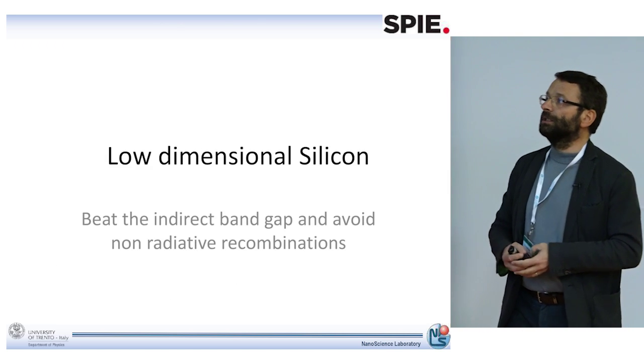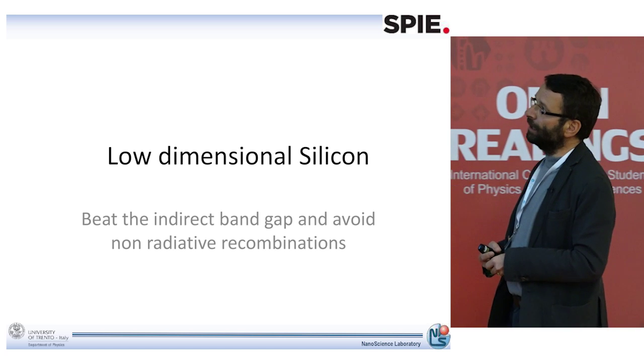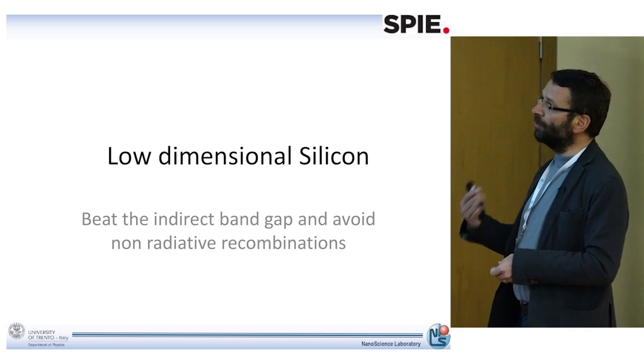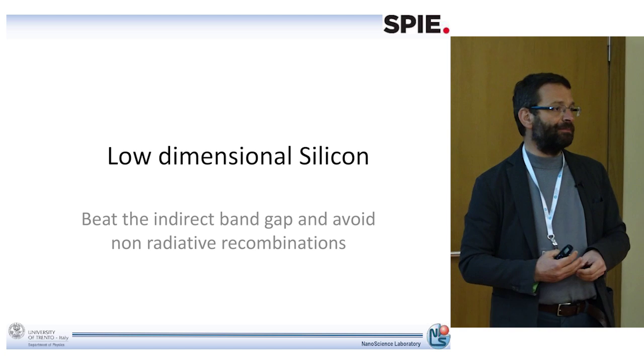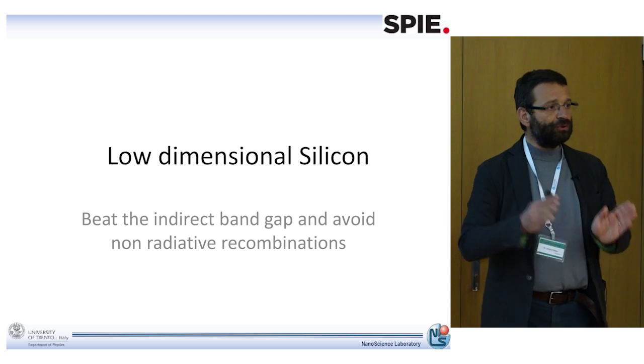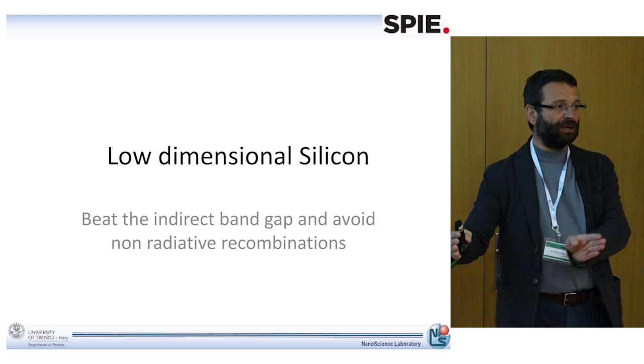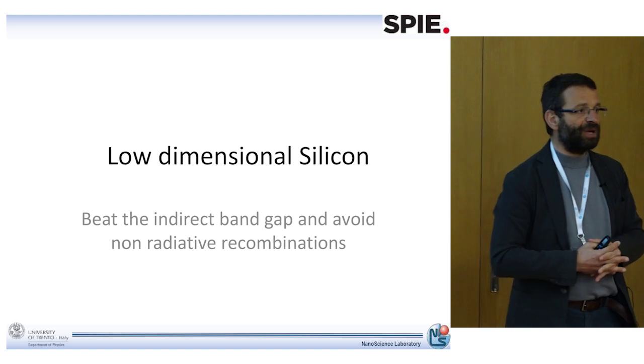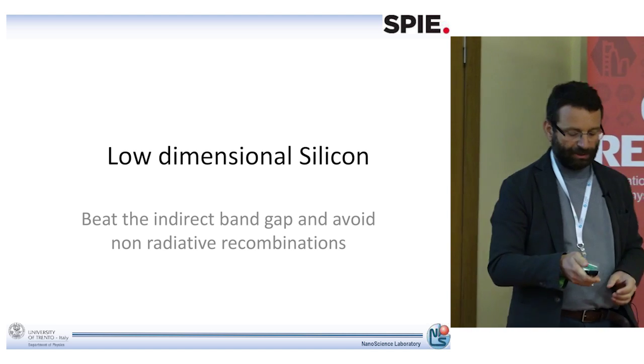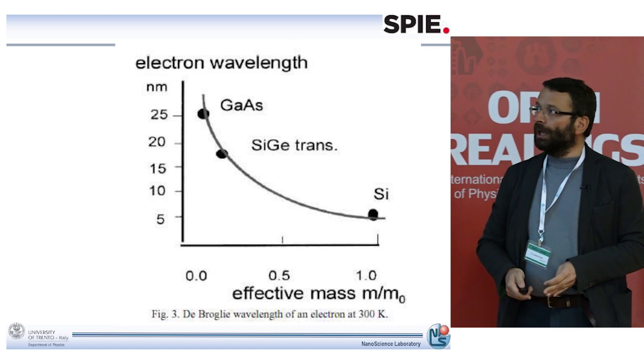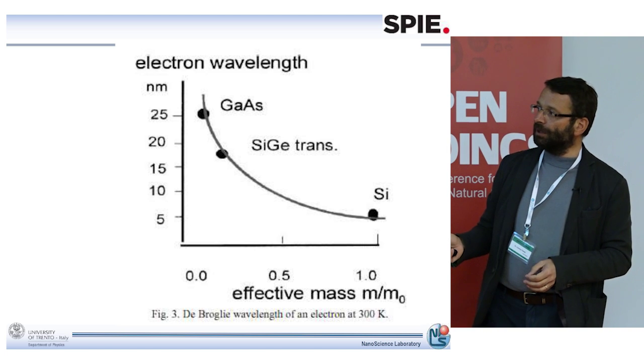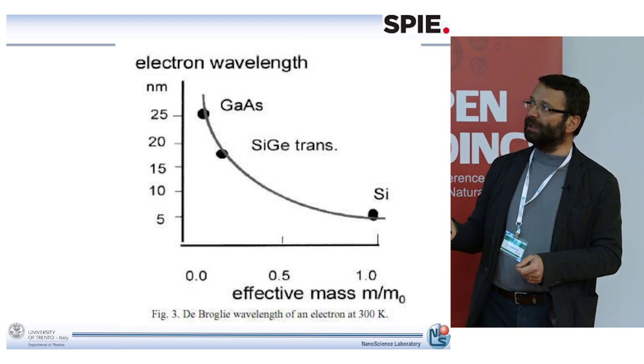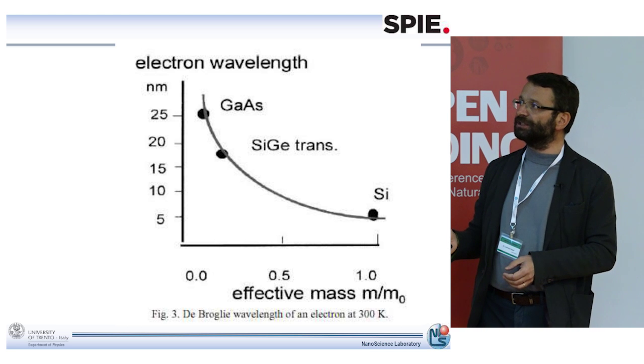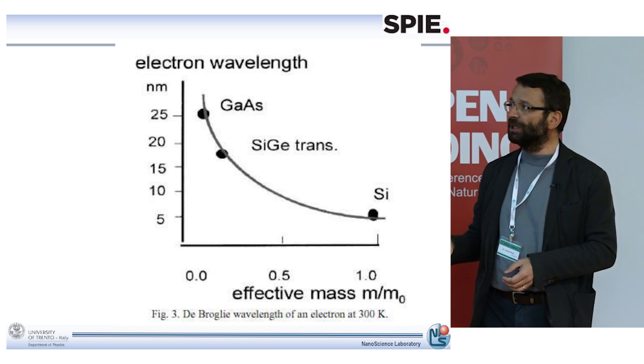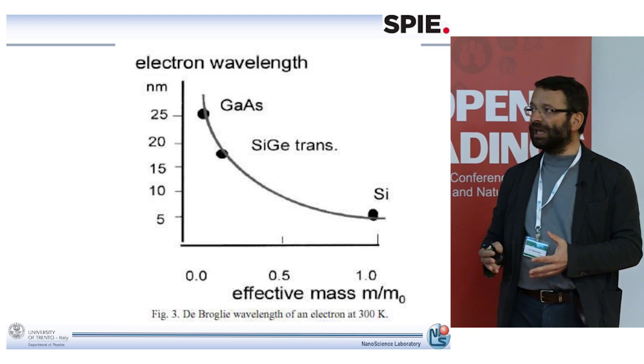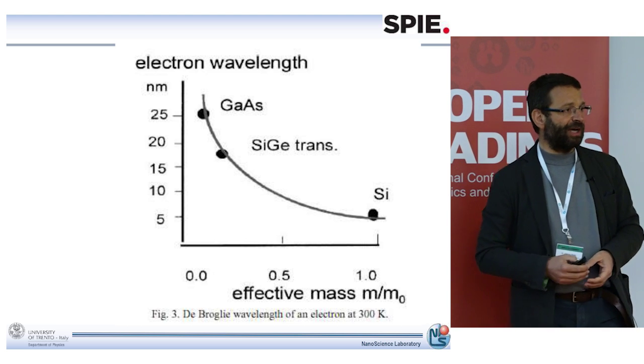And so here, low-dimensional silicon can provide a system where we can beat this indirect band gap of silicon. So we want to change the properties of silicon by simply reducing the dimension of silicon to small nanocrystals. First of all, we see that the typical electron wavelength in gallium arsenide is 25 nanometers, while in silicon it is only a couple of 5-6 nanometers.